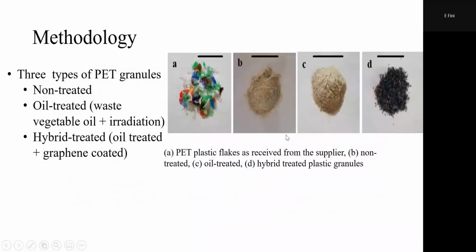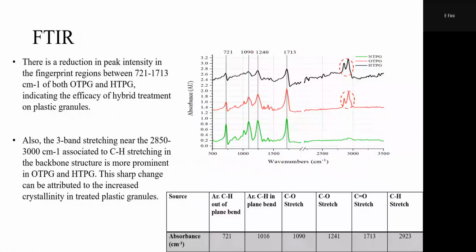But if you look at B and C here, they look the same. If my tool was the color, they're both cream color. That tool cannot distinguish the difference between B and C. But FTIR can distinguish between B and C, green and red. And on the black side it is even more noticeable. This last one, black, is the carbon treated. When you look at different peak spectra, for those of you who are not as tuned with chemistry, don't worry, there is a book that tells you what each peak means. And of course, there is a lot of literature to tell you which peak is an indicator of what.